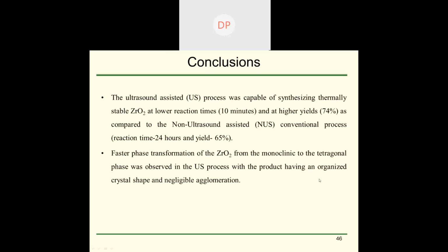Yeah. So in the concluding part, we have to give just 10 minutes of ultrasound to the reaction media, which increases the yield. So the time reduction is mainly observed here, while close to 30% is the energy saved.